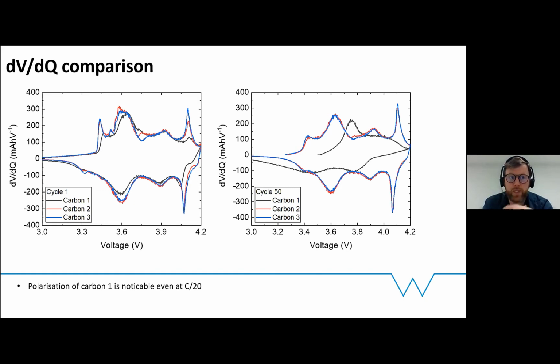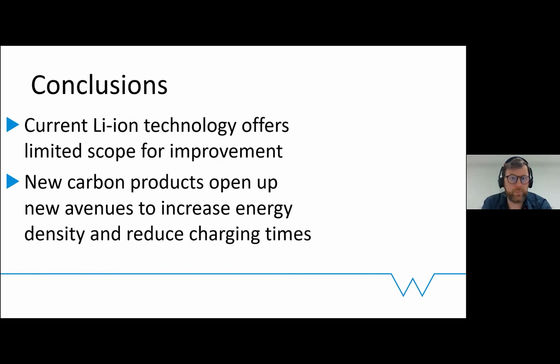So you can see how you can enable not only the stability, but the performance as well as the rate capability. So it's not a matter of just whacking something down and going thicker and hoping it works. You have to be very clever with the additives that are going in there. And you can quite clearly see from the last couple of slides the type of performance that you can get out of these systems when you add these things in. Like I say, it's a very brief overview, and I'm more open to the conversation around things.